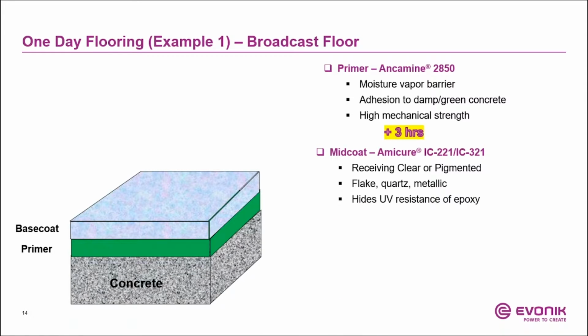The mid coat here, in this case what we're showing, is Amicure IC221 321 as a receiving coat where you would broadcast flake or quartz. What the mid coat does is help again with the durability, but also hides the poor UV resistance of the epoxy underneath. So without anything on top, this epoxy will yellow over time, but by applying the polycarbamide technology on top of it, you will hide any kind of poor UV resistance of the epoxy.